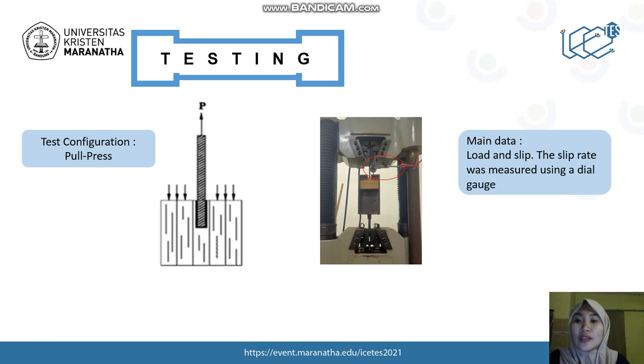Testing. The testing configuration in this research is pull-press. The threaded steel rod will be pulled and the laminated bamboo in this area will be pressed. The main data we get from the pull-out test are load and slip. The slip was measured using a dial gauge. You can see the dial gauge in this picture in the area with the red circle.